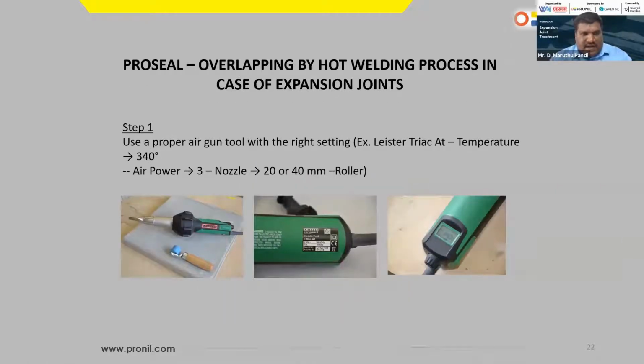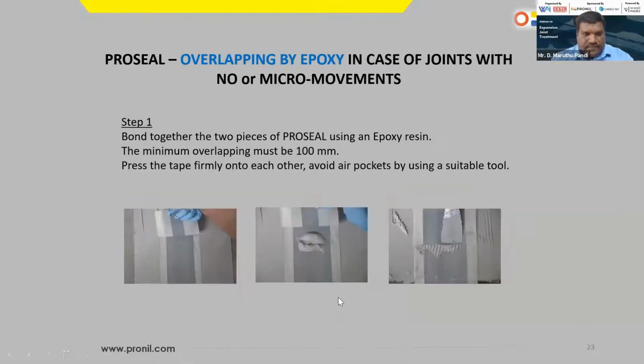This is a hot air gun, and for overlapping the Pro-Seal expansion TPE tapes, a 340-degree temperature is required to bond 2 tapes. So a minimum of 100 mm overlap is required. Even we can do it at 50 mm also. So a minimum 100 mm overlap is required to join 2 tapes. When there is a movement, we need a hot air gun to join 2 Pro-Seal TPE tapes. And if there is no movement in the joint, even we can use the epoxy adhesives. And if there are any small micro movements, you can use epoxy adhesives for the overlaps.